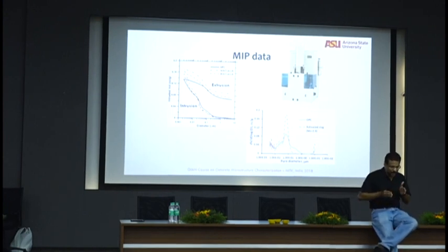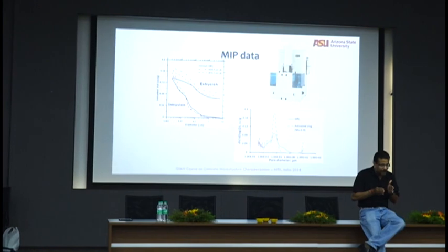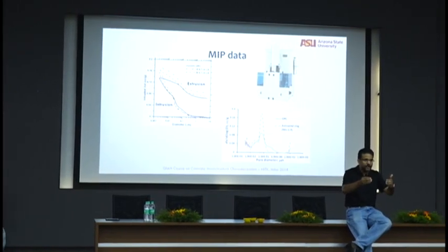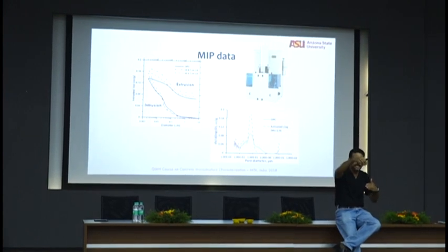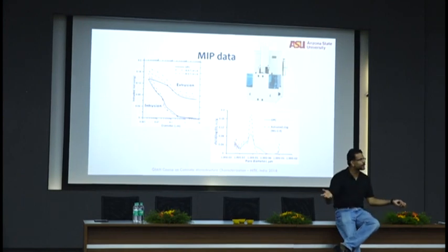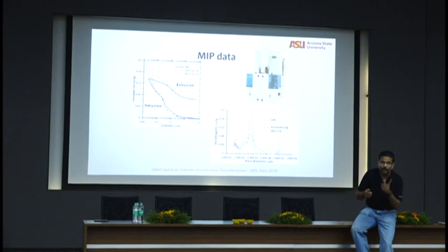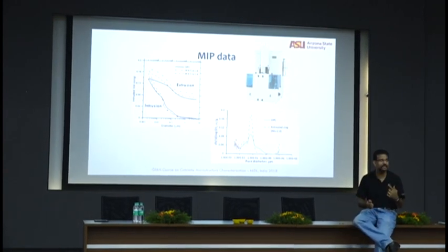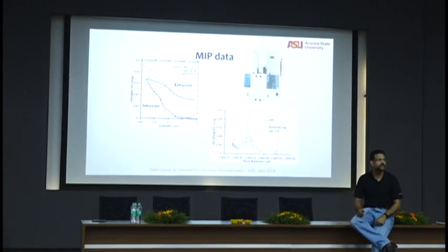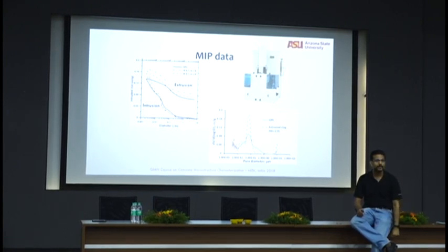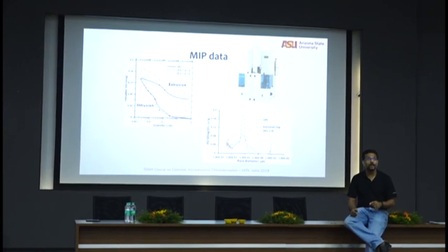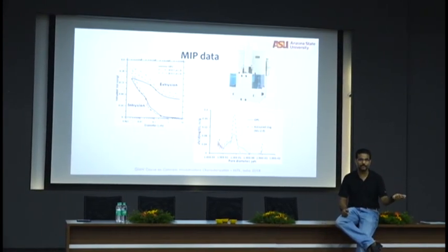So for example, you have a large pore constricting into a small pore, becoming a large pore again, right? This large pore got drained, this large pore got drained, whatever is a real small thing in between, it just stayed there. So, what does that tell you? Then, if that is the case, what can this test be used for? To find out how complicated the pore structure is.